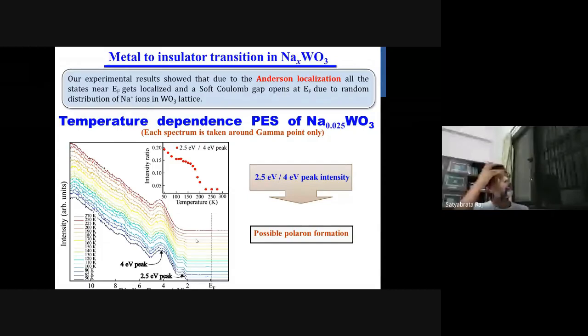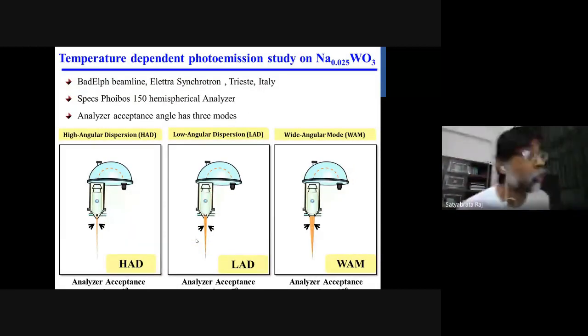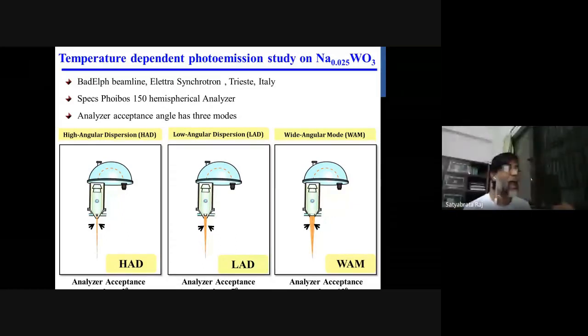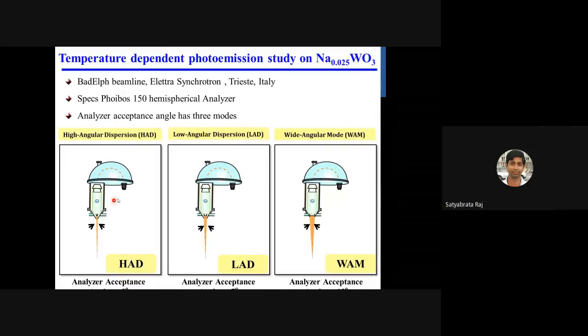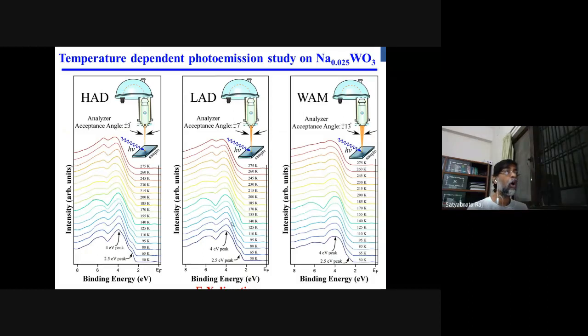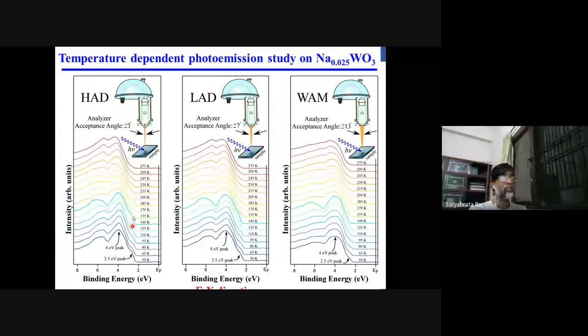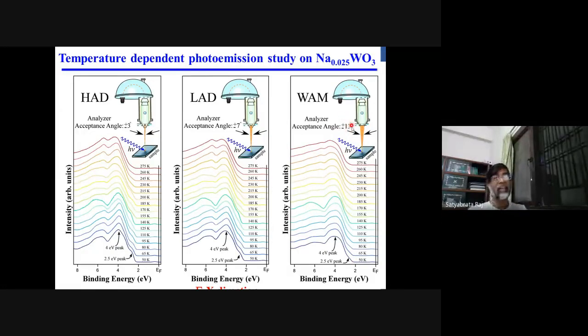To justify this, we did a special type of experiment with a special acceptance, at small, medium and wide angles, so that it can take most of the Brillouin zone. We measured the density of states around the gamma position, integrated only around the gamma position, from low temperature to high temperature. At low temperature there is a large density of states in this region, whereas if you integrate over the whole Brillouin zone with a wider angle, the density of states variation is quite low.